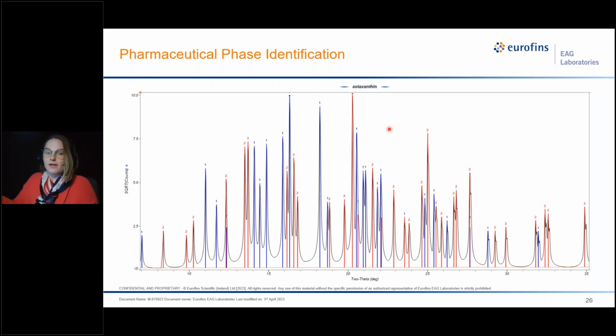So can we see different polymorphs? Yes, and this is something that's very important to think about. The other thing we can do is analyses where it's in different excipients. So if it's in a pill with other add-ins, or a cream or a lotion, or any kind of thing like that. The thing that helps us is that if we have the plain API, or active pharmaceutical ingredient, the mixture of the API and whatever substrate it's mixed into, and just the placebo without the API in it, we can compare those to make sure that the peaks you're seeing are only from your API and nothing else is there.